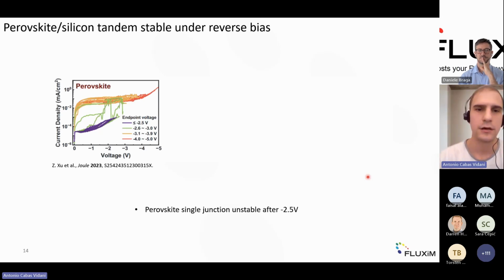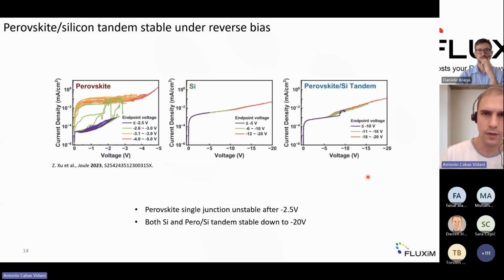But if you don't have, of course, a carbon-based electrode, as I said, it's a special kind of perovskite, then you're stuck with a single junction perovskite that is rather unstable to reverse bias, meaning that after a reverse bias of -2.5 volts, which is not large considering the variation that you might have outdoors, you have the JV that eventually is not reproducible enough. Again, I would like to stress the importance of parallel JV. It's in this way that you can get a real comparison of device stability.